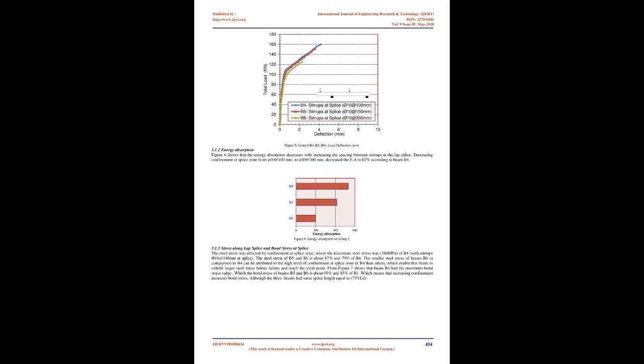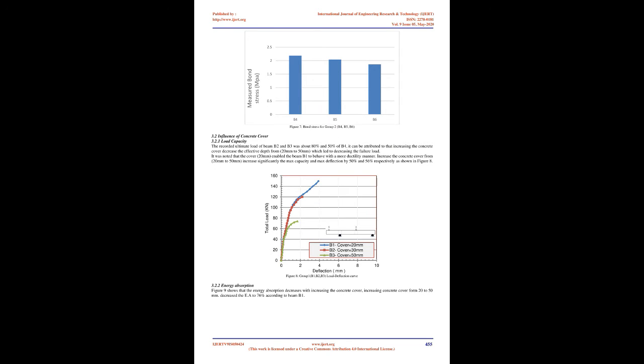The concrete strains at the max shear strength were measured using an extensometer and DEMEC points, with a distance between them of 100 mm, and they have been fixed on the concrete surface at maximum bending moment and at mid-span. The reinforcing steel strain was measured at the start, the middle, and the end of splice length using 120 ohm electronic strain gauges. 2.5 Test Setup and Loading Procedure.